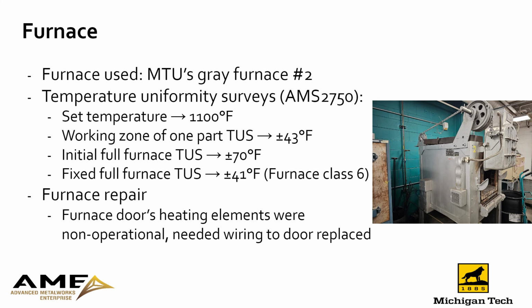So before we can quench parts, we've got to heat them up first. To do that, we're going to use MTU's Gray furnace number 2. We did 3 temperature uniformity surveys on that using AMS 2750G with a set temperature of 1100 F. The first survey had a working zone of just the dimensions of one part, and that had a temperature uniformity of plus or minus 43 degrees F. Then we did a full furnace temperature uniformity survey that had results of plus or minus 70 F.